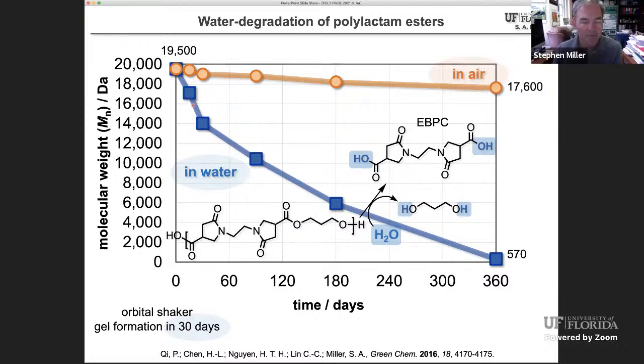And as we continued this experiment and measured the molecular weight by GPC as a function of time here, we found that after a year, essentially 360 days, the number average molecular weight, if you will, was pretty close to our lowest standard. So essentially it was hydrolyzing. And the polymer was losing its mass fairly rapidly in the course of a year, even though it's just a simple polyester with an amide pyrrolidinone ring in it.